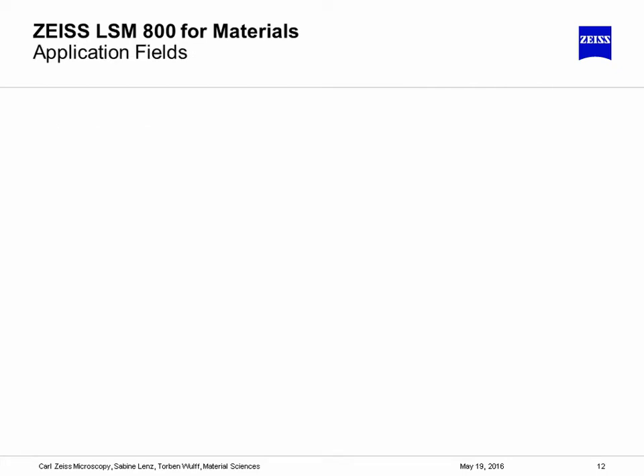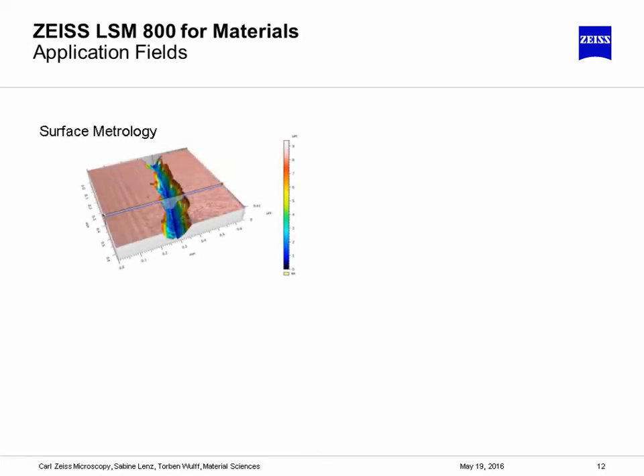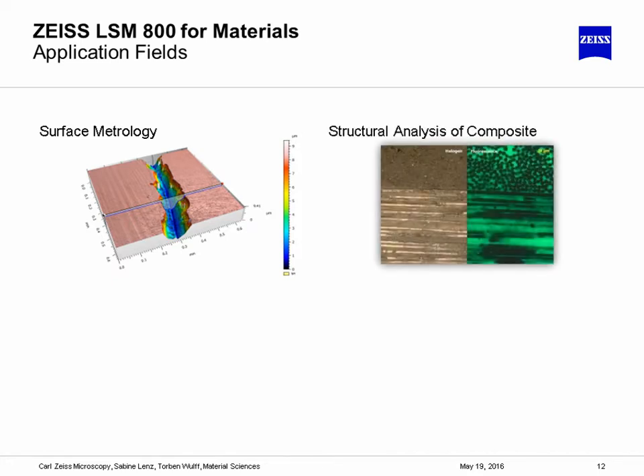Looking a little bit more closely at this, what we see in terms of application fields for this technique is quite diverse. So surface metrology, this is a scratch that's been placed into a specimen. You can quantify the volume here and the exact roughness or profile of that scratch. That could be applied to maybe a wear track or some type of a tribological investigation.